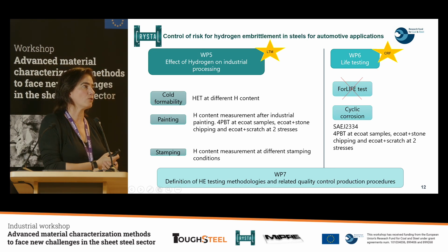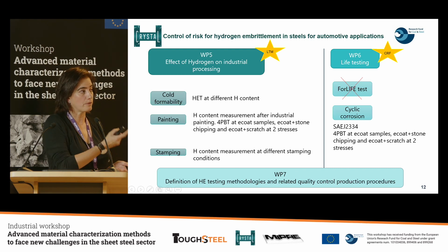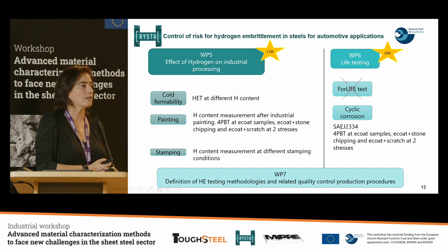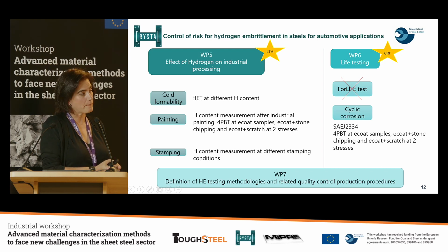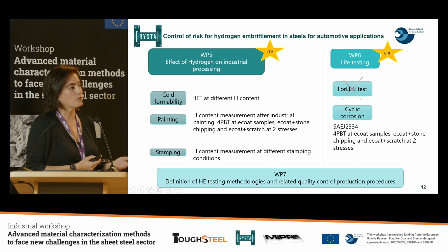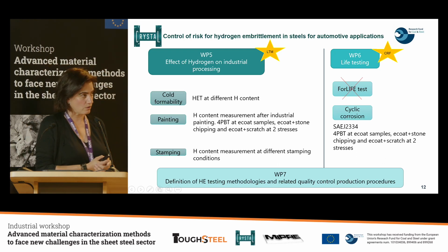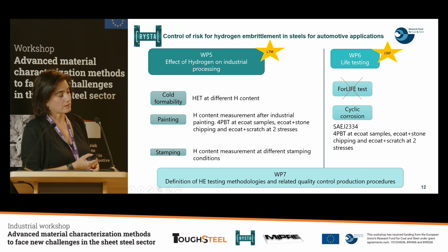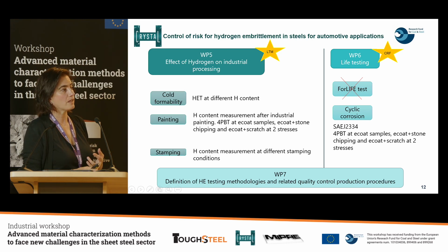Here it was planned to do the ForLIFE test, but due to economical reasons, CRF couldn't perform it. And we decided to increase the number of the samples tested in cyclic corrosion and increase the number of inspections. So the selected cyclic corrosion test was SAE J2334, and we tested the same samples as in the painting in work package 5. So the samples E-coated plus stone chipping, and E-coated with scratch with 2 different stresses.